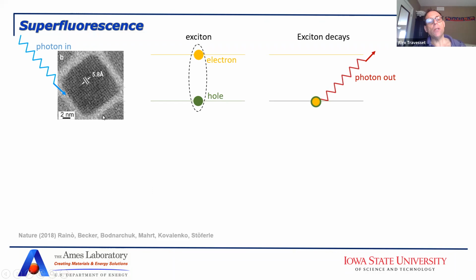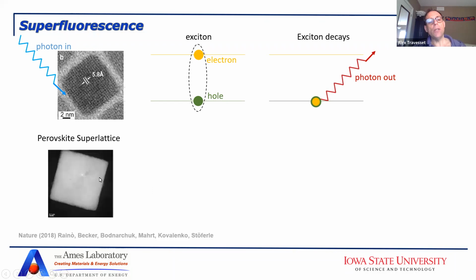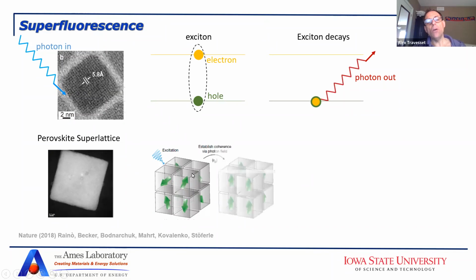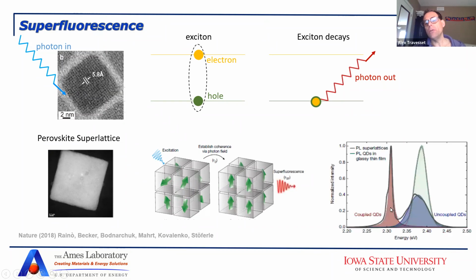However, when you put these nanocrystals in a superlattice, something interesting happens. When you have a photon in, it doesn't decay automatically, but you form a coherent state where nothing happens, but all of these excitons become in phase. And then eventually they radiate, they decay, but they decay all at once and emit a superfluorescence pulse, which is something that you can see here.